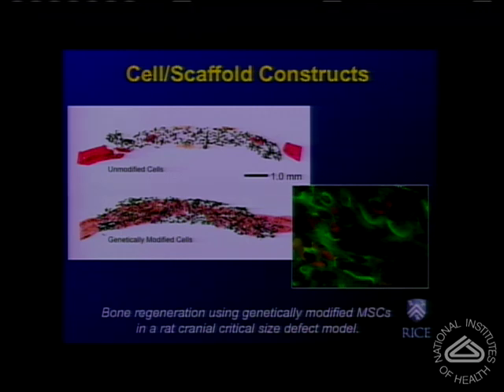This is the host, the edges of the host bone. This is the defect that is filled with a material. The material is a titanium fiber mesh that in cross-section appears as a black dot. And when we have genetically engineered cells, we have bridging of this critical size defect.